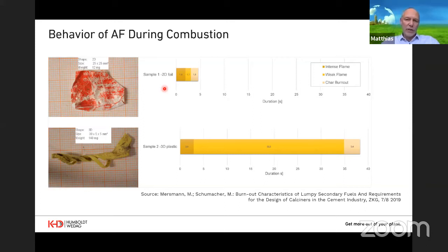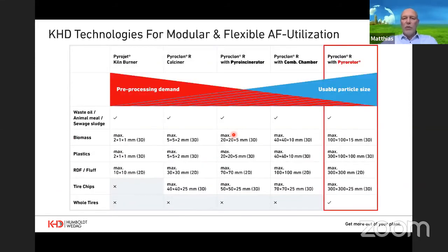We've conducted combustion tests, and we've taken the time it needs to ignite, fully burn or weak flame burnout and char burnout. And you can see from the comparison of these two plastic parts, while the lower one is also not a big part, but it consists of more dense material, this burns out in only 30 seconds. And if you compare that to a coal flame or a fossil fuel flame, you see that the way this ignites and the way it releases its heat is completely different. And so the alternative fuel technologies have to take account of that. In order to do that, KHD has developed a wide range of technologies to use alternative fuels.